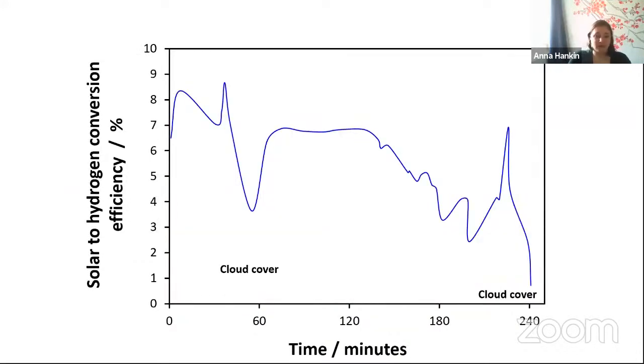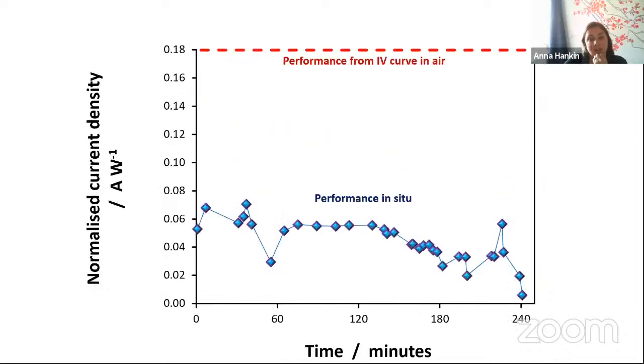I wouldn't publish this result, and it remains unpublished despite several years from the experiment, because the project had to stop and we didn't really have time to finish it off. But the solar to hydrogen conversion efficiency we got was between 8% and 4%, and the jumps are due to this inaccurate measure of the solar intensity that actually reached the electrode.